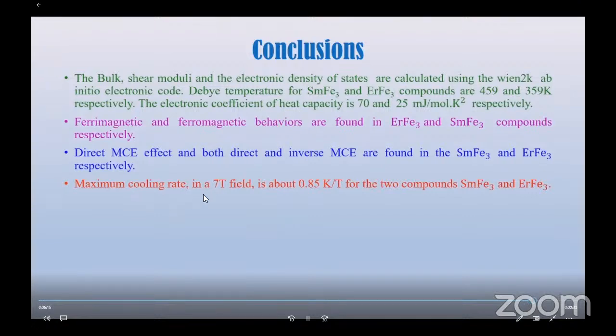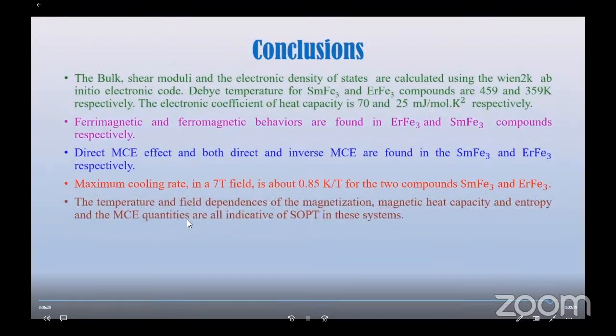Maximum cooling rate in a 7 Tesla field is about 0.85 Kelvin for each Tesla for the two compounds, samarium iron 3 and erbium iron 3. The temperature and field dependence of the magnetization, magnetic heat capacity and entropy, and magnetocaloric effect quantities are all indicative of a second order phase transition in this system.